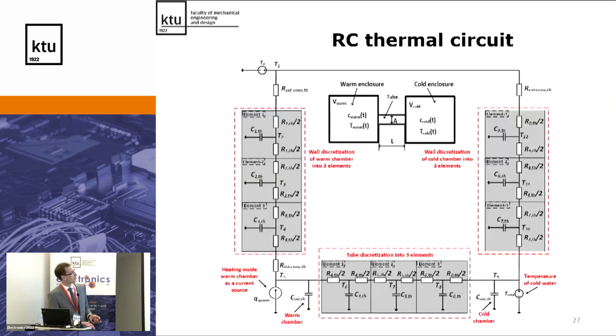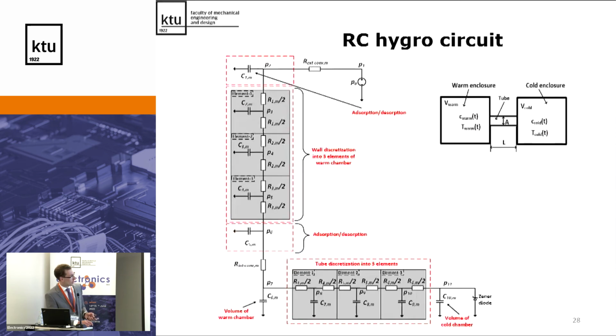And here's the thermal circuit to model the temperature field. Here we have the cold temperature of cold water, and we represent it in 1D in this case, with thermal flow through the metal wall, and then here's the representation of the tube, and then here's the wall of the warm chamber enclosure. And then here we have a moisture circuit, or in other words, a hygroscopic circuit, where we have a moisture flow through the plastic of the warm enclosure, and then only moisture transport through the tube. And here we neglect the metal wall, because metals don't absorb moisture.